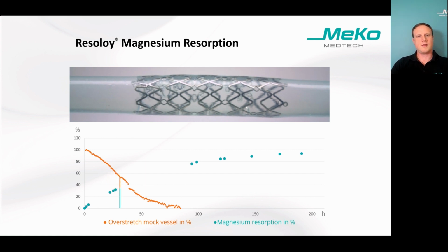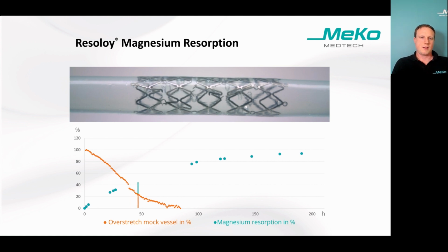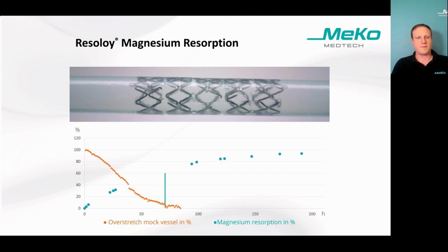So now the vessel is nicely overstretched, and as degradation occurs, so as corrosion occurs, the radial force of the scaffold goes down. I have to say that this degradation rate, of course, is accelerated in this test. In vivo, the degradation rate would be much slower, but I will come to that later on.